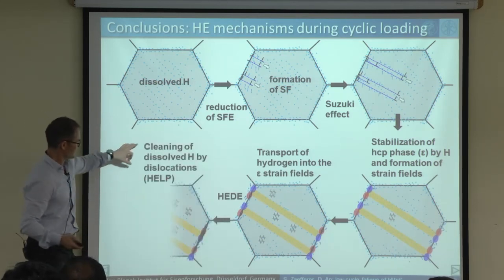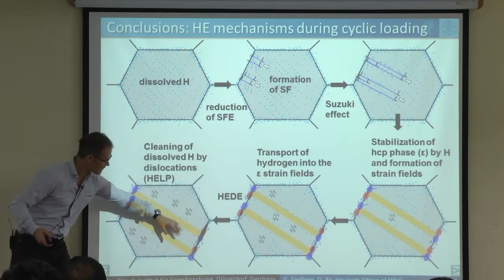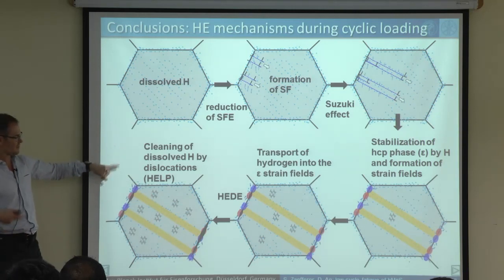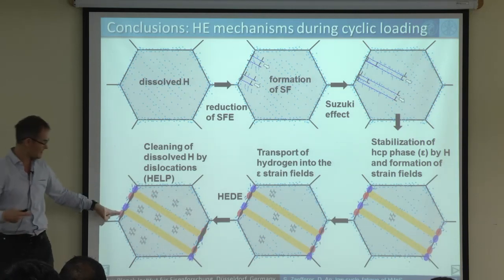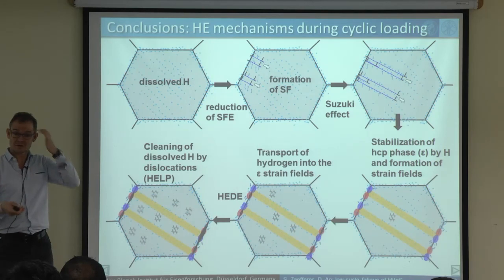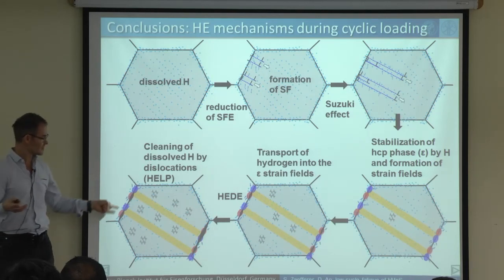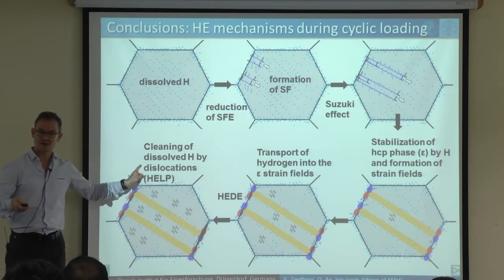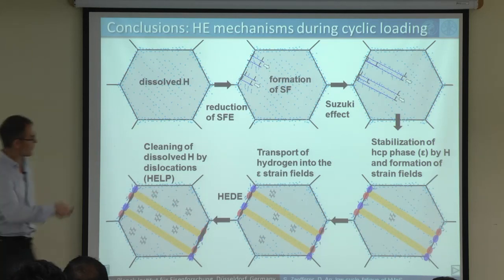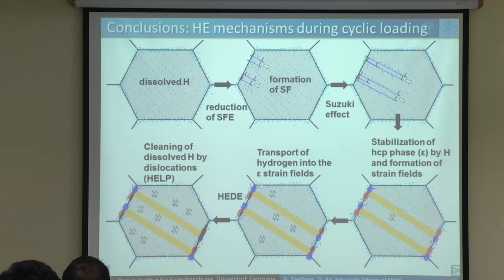And finally, we also have a cleaning of the microstructure by the dislocations, so we get an additional hydrogen embrittlement by the HELP effect, by hydrogen enhanced local plasticity. So all this comes together: Suzuki effect, reduction of stacking fault energy, stabilization of epsilon phase, HEDE effect, HELP effect, everything together to make this embrittlement. It's rather complex actually.